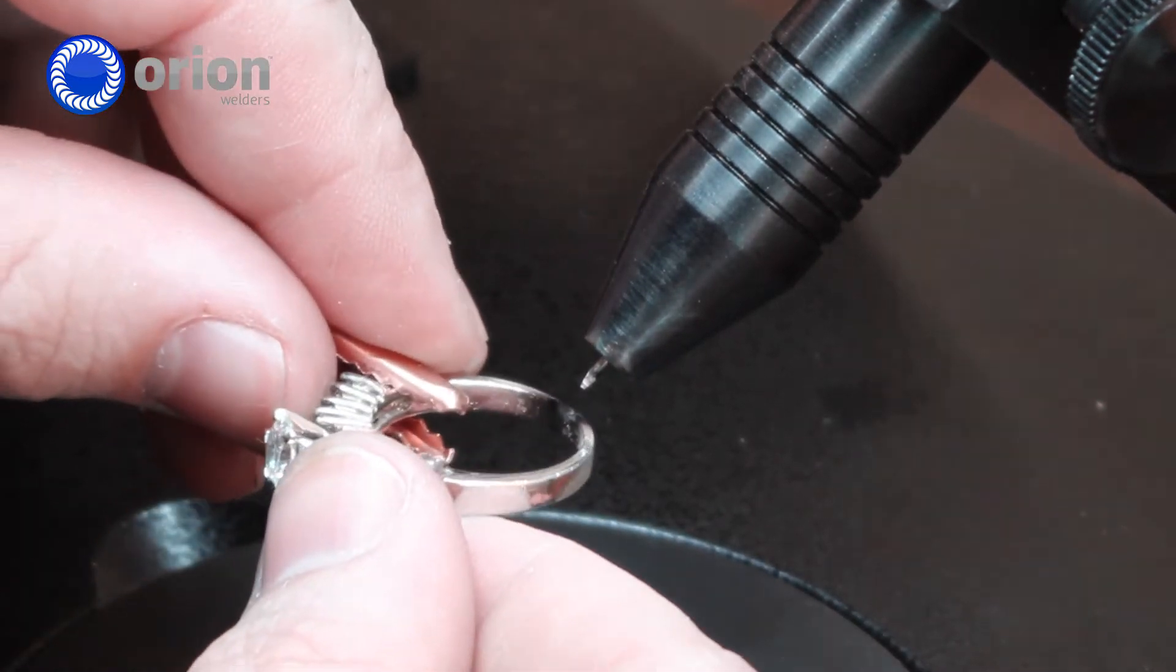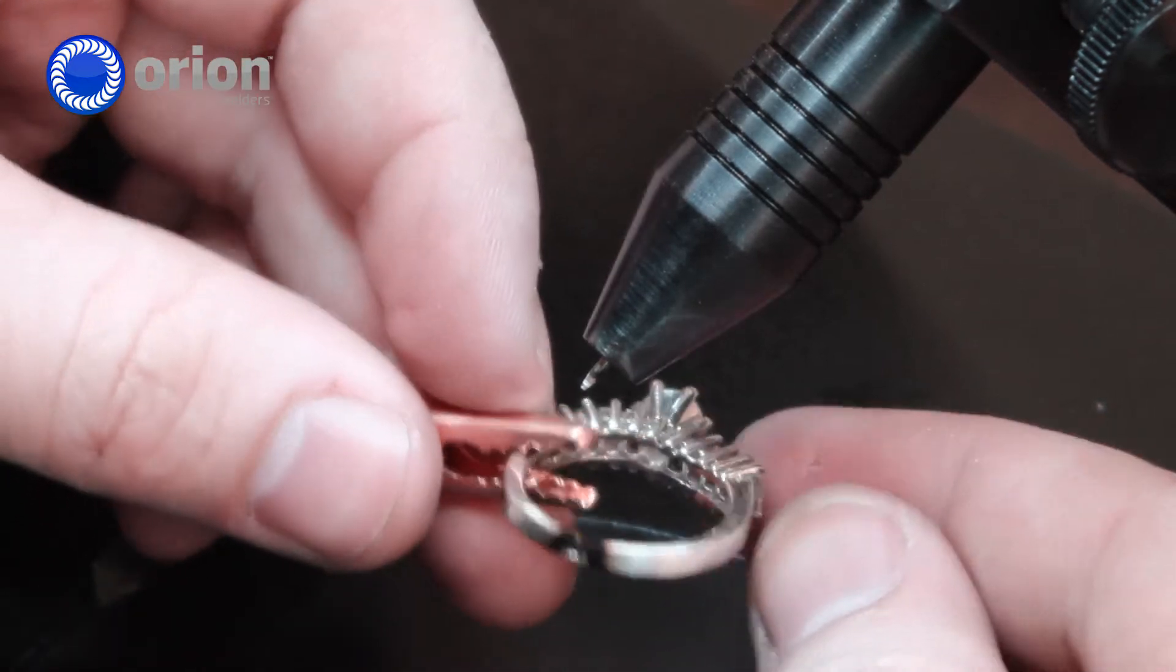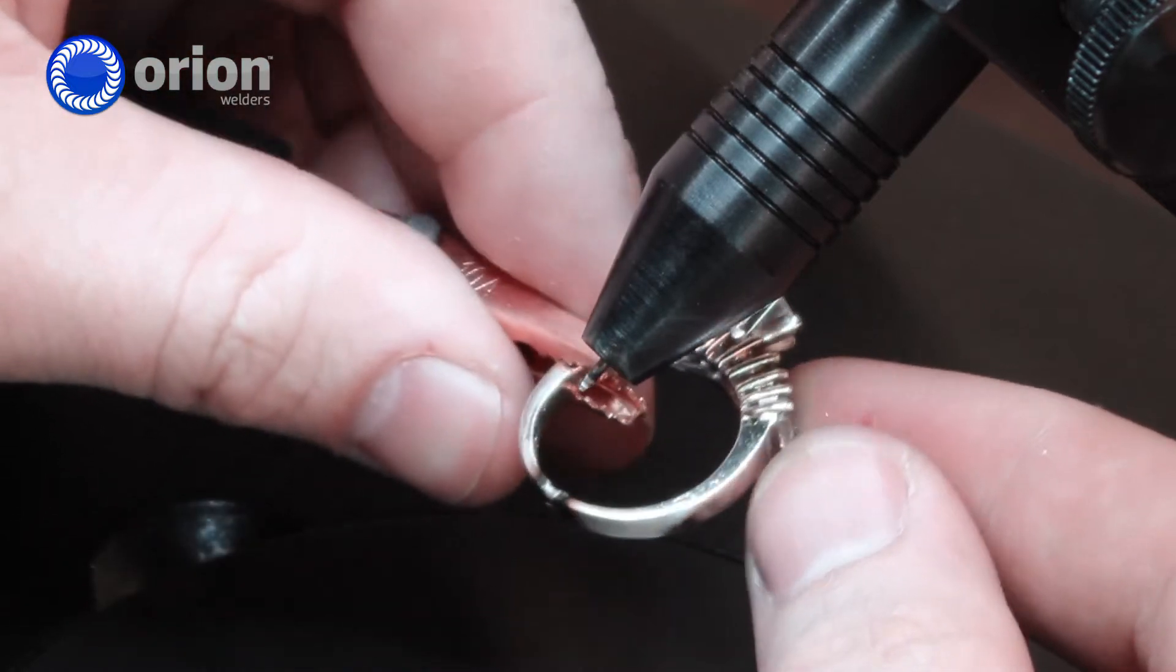So I'm going to go to the side of the ring. Now there will be holes that are created. You can simply hit the hole again to fuse the metal from the surrounding area and pull it into the joint where the weld is happening.